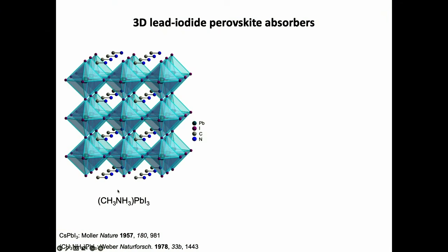So for example, here I'm showing you this material, methyl ammonium lead iodide, where you will see lead at the center of the octahedra, and there are iodides at the vertices, and these octahedra propagate in 3D space by sharing corners to form this turquoise framework. This is your standard perovskite framework. This turquoise framework has a negative charge, so you will find positive ions residing in the cavities defined by these 8 corner sharing octahedra. So here I'm showing you methyl ammonium. Chemists don't show hydrogens in their crystal structures, mostly to confuse people. But trust me when I say this is methyl ammonium.